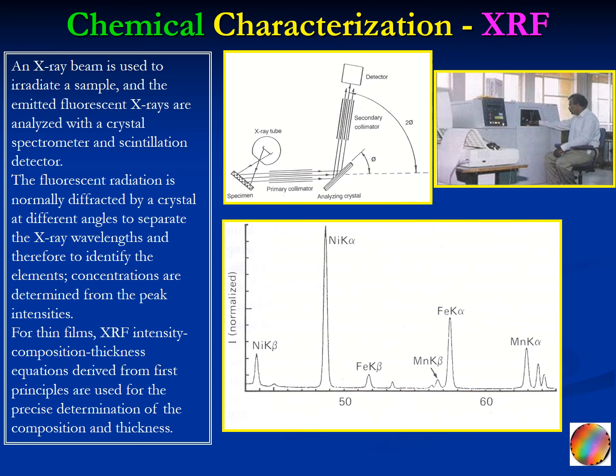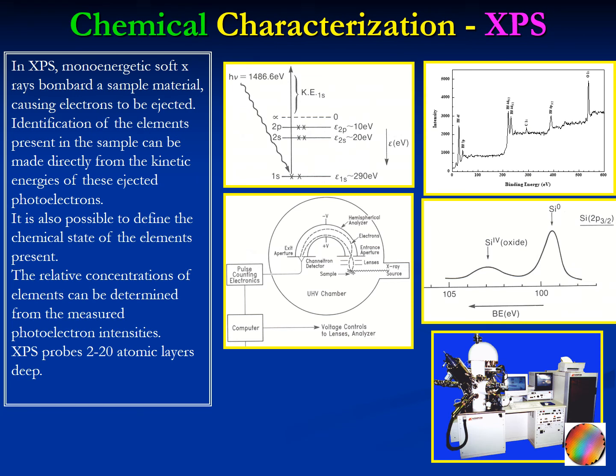In XRF, you detect the emitted X-rays by the sample. In XPS, you detect the photoelectrons emitted by the sample when it is bombarded by the X-rays. This is a very powerful technique. It can tell us the composition of the film, and most importantly, it can tell us the oxidation state of the elements making up the film, which can be extremely important in many processes like catalysis, corrosion, and sensing. It is a surface technique, it's not a bulk technique, so it can detect only the few top monolayers of the film.